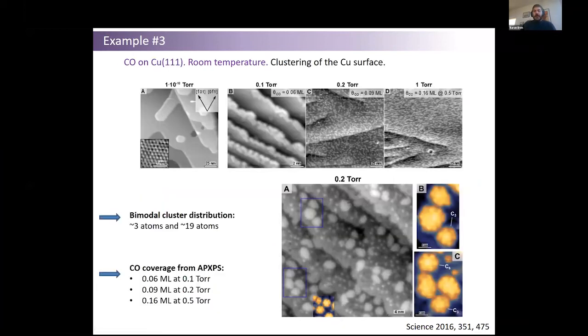Now we are in year 2016. This is a work of mine. And it's the first time that now we show that clustering does not only happen on the stepped surfaces, which are a bit less stable, but it can also happen on the most dense and compact 111 surfaces of, let's say, FCC metals. This time it's on copper.